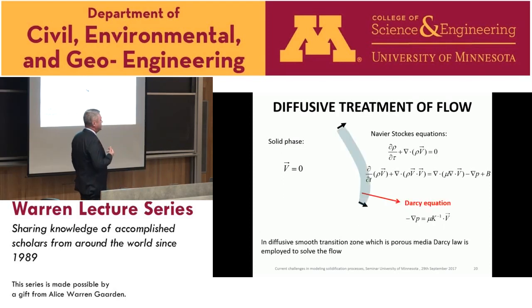So, the main idea, and you can find it in most of the books related to porous media, is to introduce the so-called Darcy equation. The Darcy equation works in this diffusive interface. In the diffusive interface, we can say this is a porous media, that means a combination of solid and liquid particles. In that porous media, instead of that complicated equation, we can have this equation. I can calculate V if I know this constant, which is a porosity constant, and if I know the pressure field.